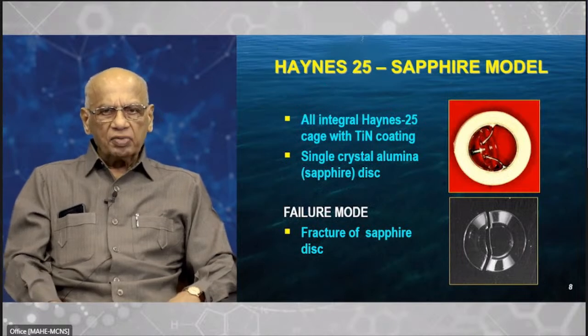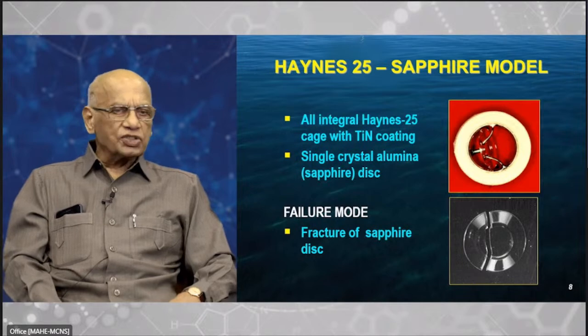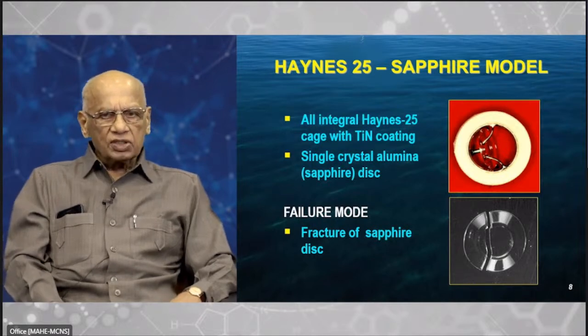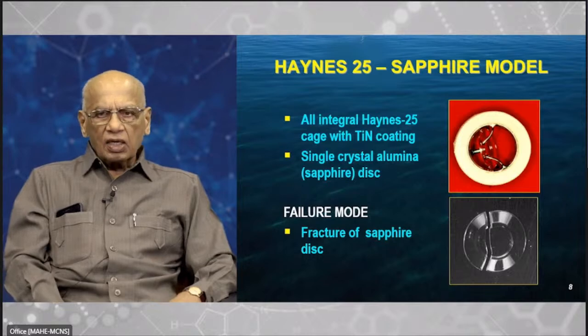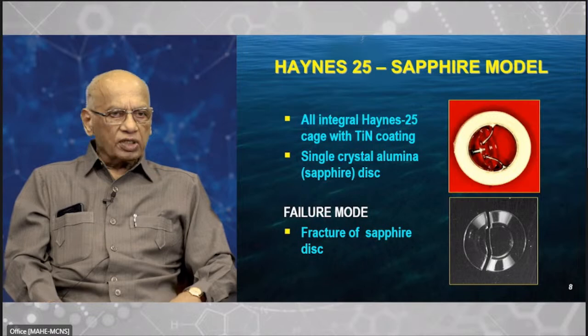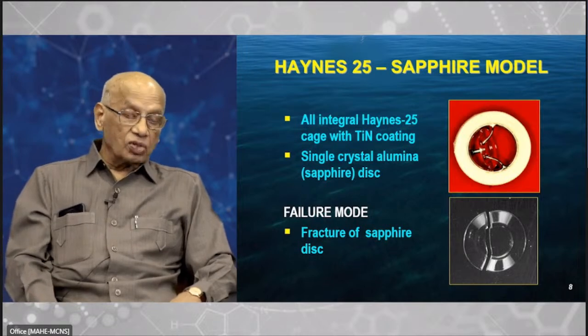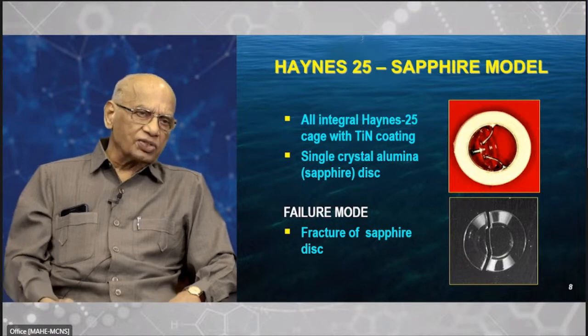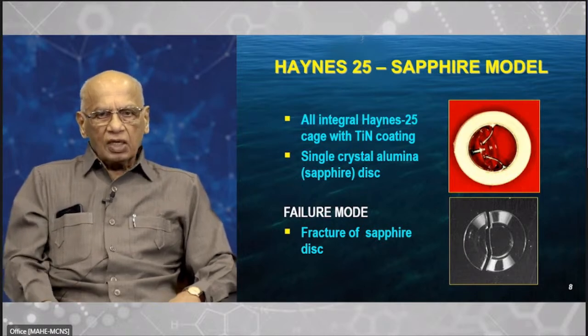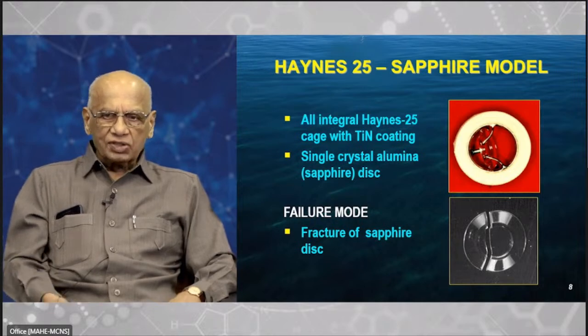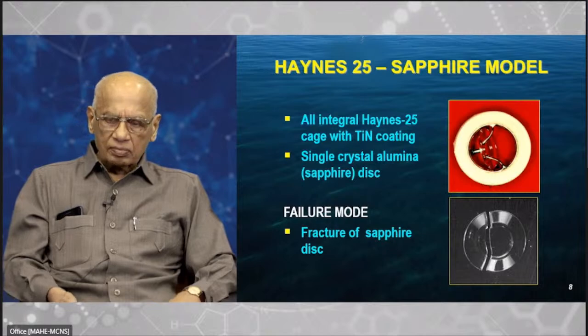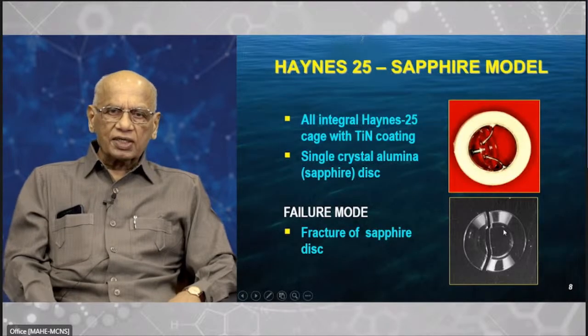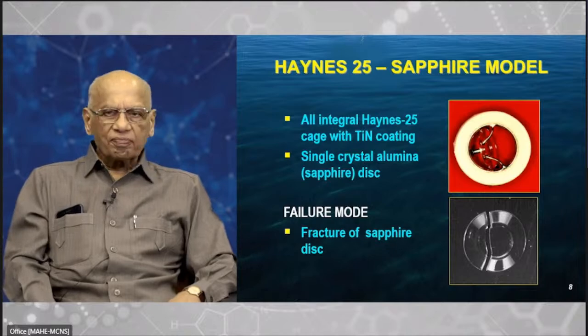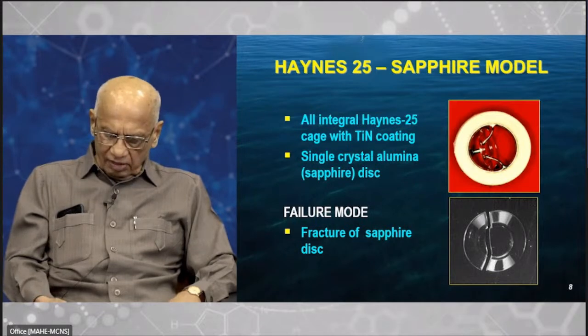Now here the all-integral cage remains, but we had changed to HAYNES 25. Titanium was not acceptable. Single crystal alumina remained the same. And we also had a titanium nitride coating, because that makes it further blood compatible or totally inert, so that blood cannot damage it. That was an additional protection. Now this failed because the sapphire cracked. You can see the sapphire is cracked. So the cage is all right here, but the sapphire has cracked. So this also was a failure. Then we moved to the next.